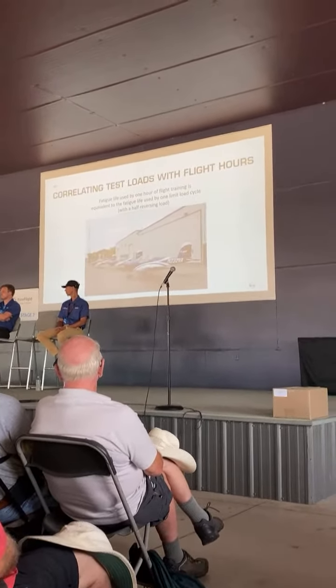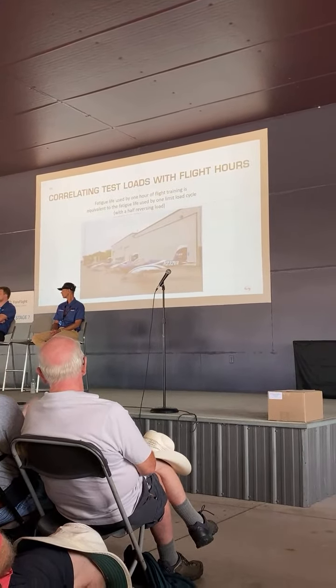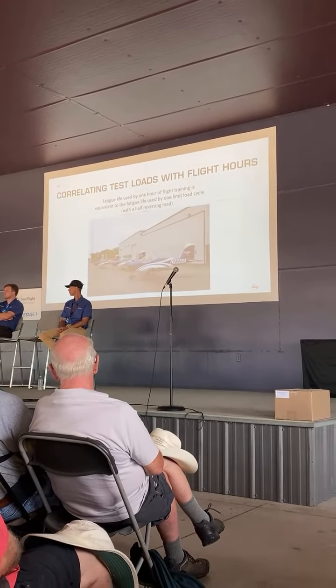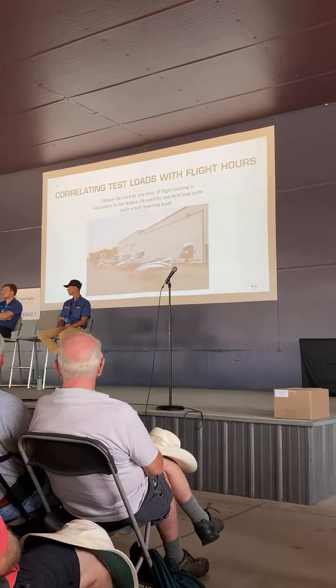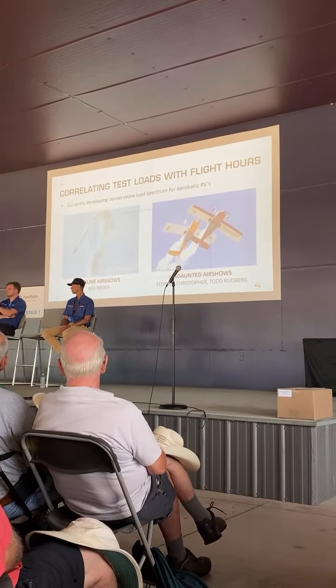Again, we already covered this. So you take a coupon, and if you load it fully in tension and then go to half reversal, those are the coupons that have the bend edges on the side, so we can actually apply compression with a half reversing cycle, some compression. That's the equivalency. We've gathered data from redline air shows and non-jet air shows. We're comparing those two independently to come up with a further reduction for what you'd expect in aerobatic application of the other airplanes.